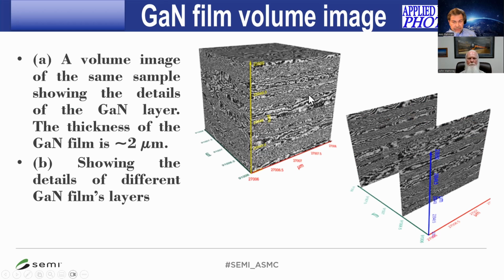If we take that volume image, we can extract the layers. Here I am showing two layers on the XZ plane along the y-axis. I have one slice here, one slice there. As you see, if you go through the whole structure, the lattice arrangement changes, and we are able to quantify that. This is only a 2 micron by 2 micron by 2 micron structure, and within that 2 micron thickness on the z-axis, as you can see, some layerification, for lack of a better term, has happened.